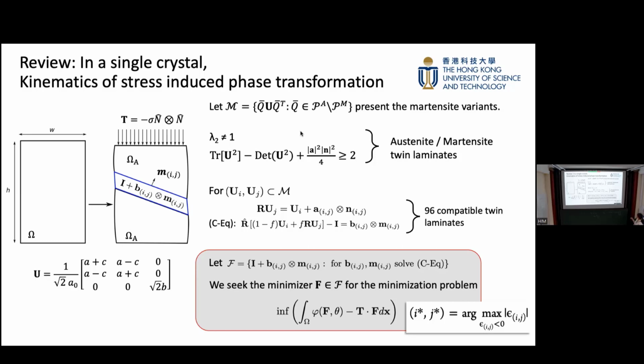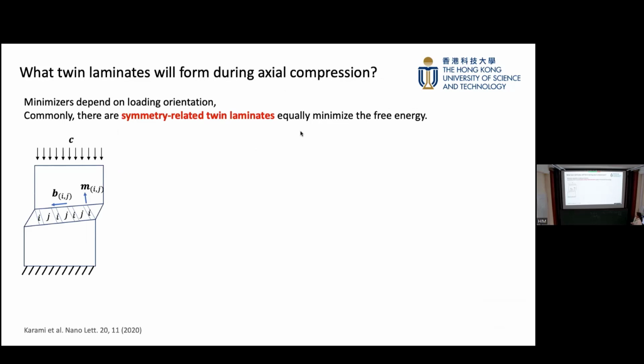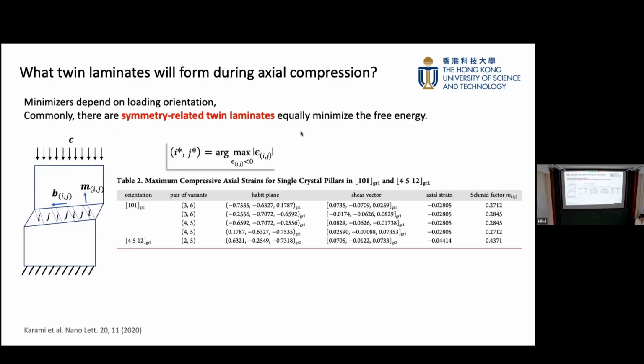So we actually use this max to find out exactly what twin laminates will form under the specific loading orientation. As you can see, this really depends on what orientation you load. Obviously, among the minimizers, there are some symmetry related laminates in that set. For this specific material, we find the pair of variants that can form for orientation 101. There are several, and they maximize the compressive axial strain, and that gives the same values here.